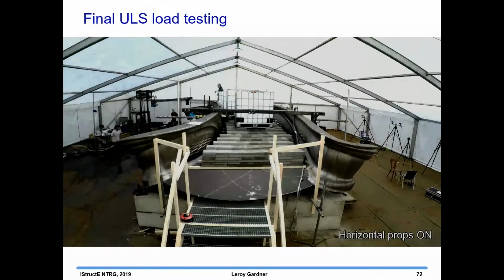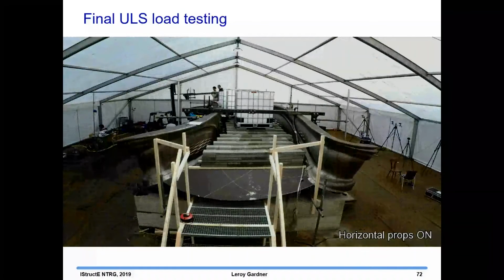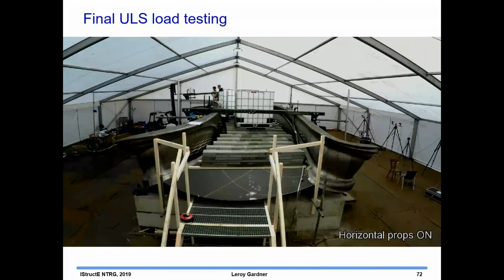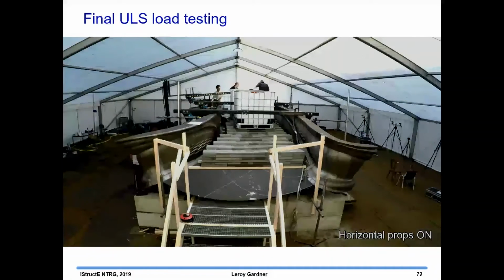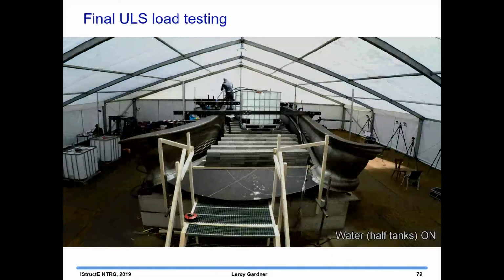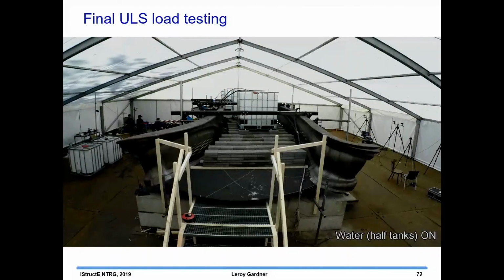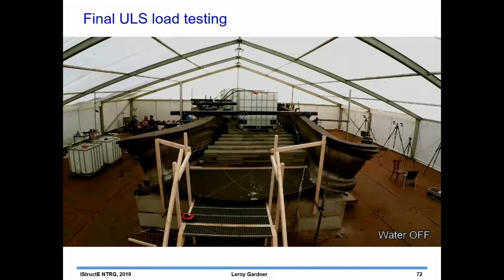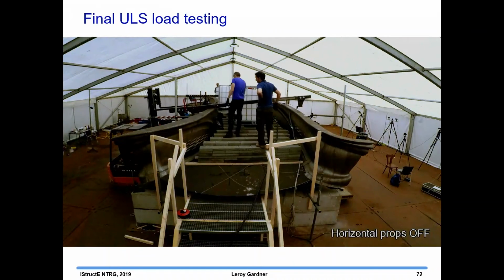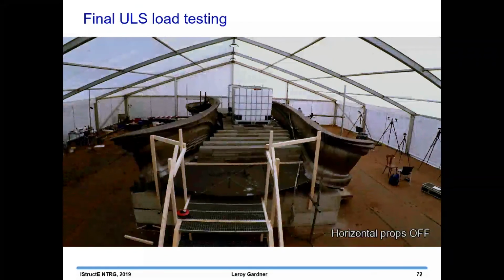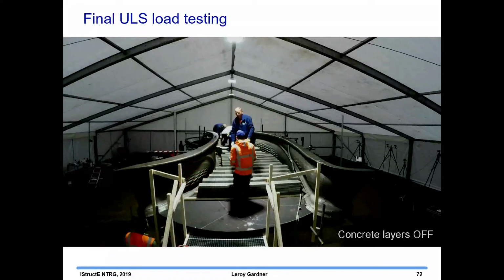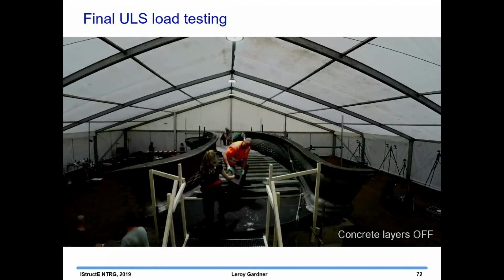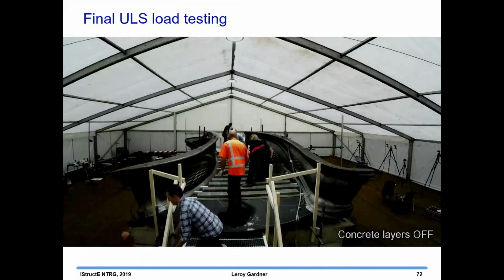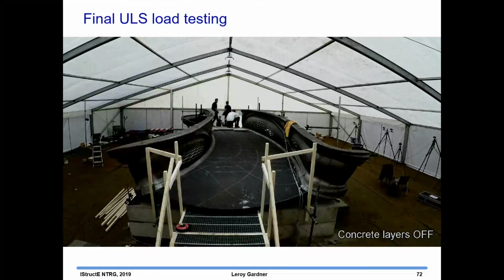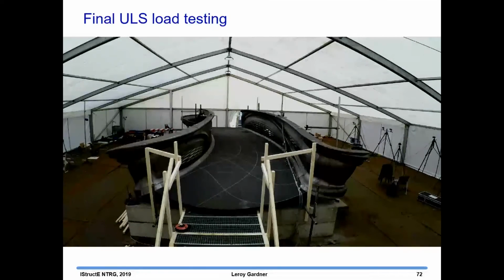We then, at a slightly reduced vertical load level, also applied some horizontal loading. And these were done using these props with hydraulic jacks attached. And so we jacked the bridge in and we pushed it out. And then we took everything off very quickly. And finished.